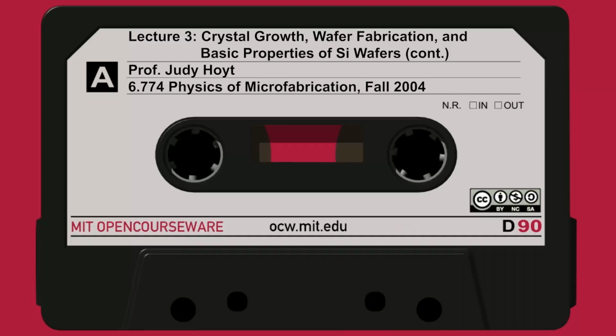This is a measure of the purity of the silicon, a generation lifetime, tG, that goes like 1 over sigma, which is given by this number, times the thermal velocity, which is also a constant, times NT. NT here is the concentration in per cubic centimeter of traps. Typically the cross-section sigma for a typical deep level is this number, 10 to the minus 15th. I know the thermal velocity, so I can solve for NT. This requires that I have less than 10 to the 12th per cubic centimeter, or 0.02 part per billion, of these traps in the semiconductor.